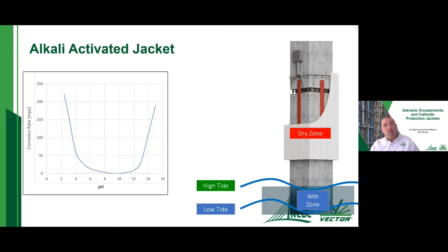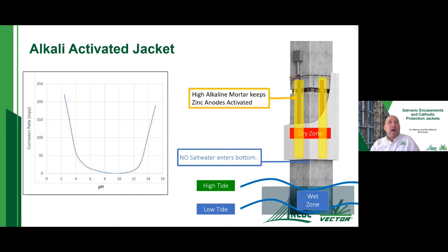So again, we have our wet zone. There is no water going into the bottom of our jacket system. And we have our alkaline mortar that's surrounding the anodes. So the zinc is only being activated by this mortar. It's not being activated by the salt water. Again, we're relying on this high pH of this mortar to activate the zinc, and at the same time, it's not going to be detrimental to any of the reinforcing steel that we have in the jackets as well.